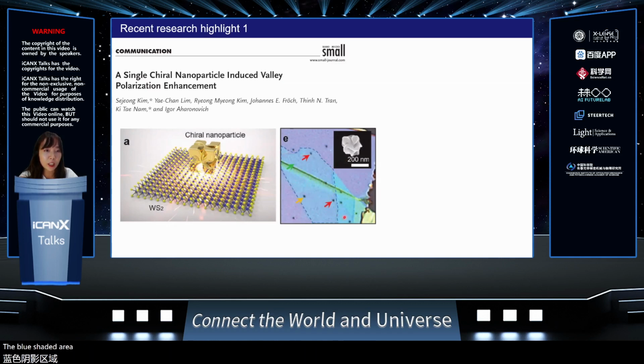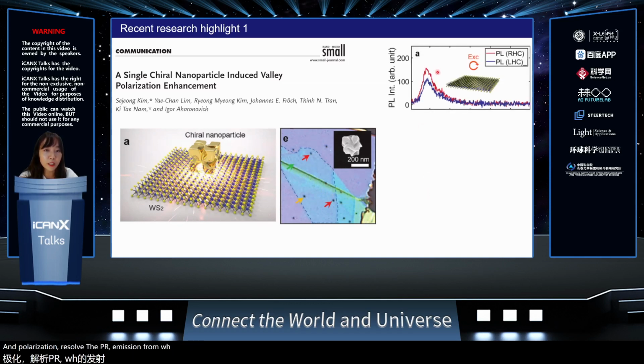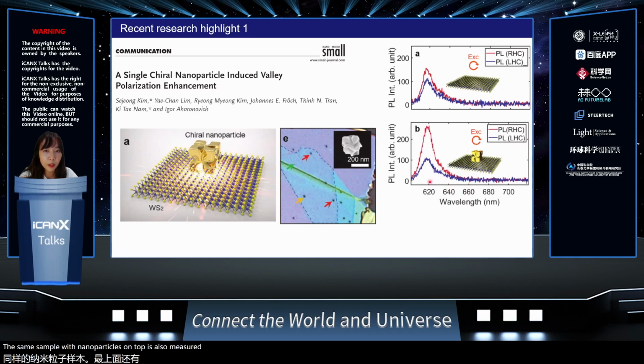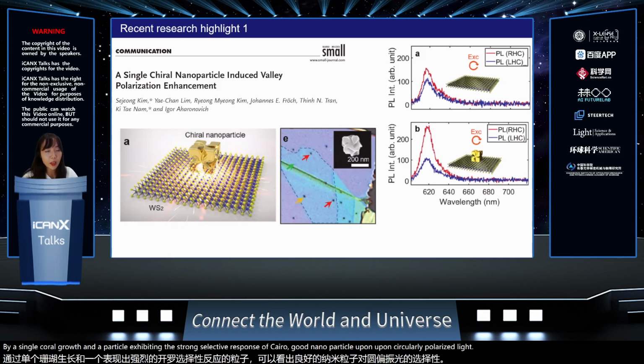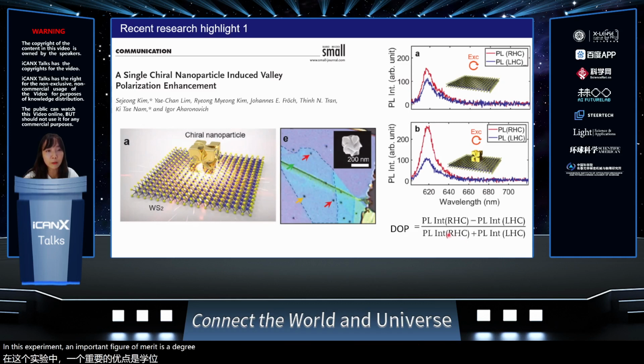The blue shaded area here is the monolayer WS2, and the black small dots are single chiral nanoparticles. Polarization resolved PL emission from the WS2 sample without any particles is measured first under room temperature and ambient condition. The same sample with nanoparticles on top is also measured. And notably, the valley polarization is dramatically enhanced by a single chiral gold nanoparticle, exhibiting the strong selective response of the chiral gold nanoparticle upon circularly polarized light. In this experiment, an important figure of merit is the degree of polarization, which is the normalized PL intensity difference. In this work, a large degree of circular polarization of up to 0.45 from a monolayer WS2 is measured.